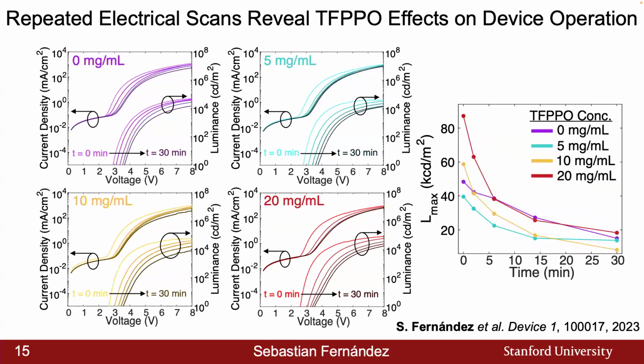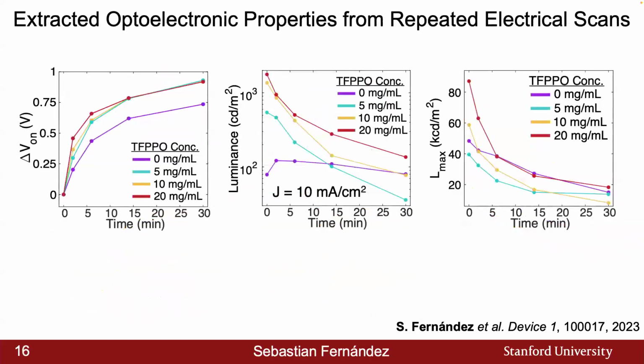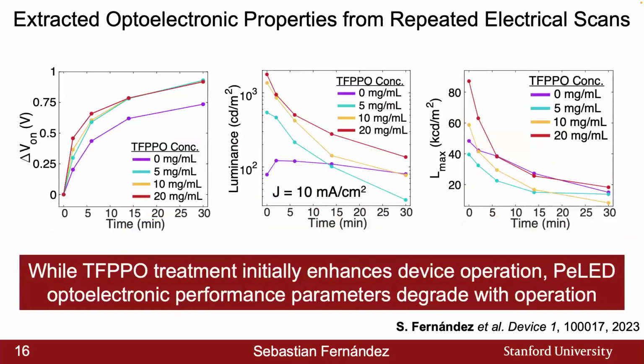And lastly, if we look at the evolution of the maximum luminance of these devices, we can see that in general, the ones with lower TFPPO concentration might start off at a lower maximum luminance, but are overall a little bit more robust, showing their integrity and applicability for high brightness applications such as laser diodes. And so by putting all of these together, what we can say here is that the TFPPO treatment might initially improve the LED performance, but however, the optoelectronic parameters do degrade with operation, really suggesting how TFPPO is influencing the optoelectronic parameters within the device itself.